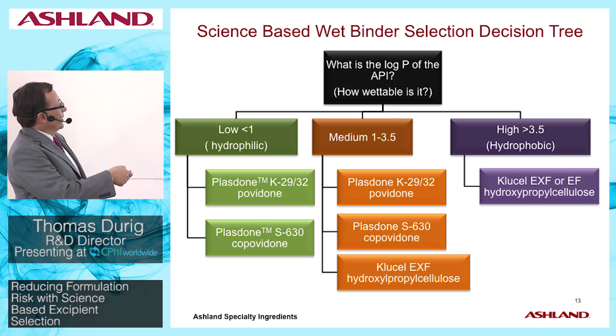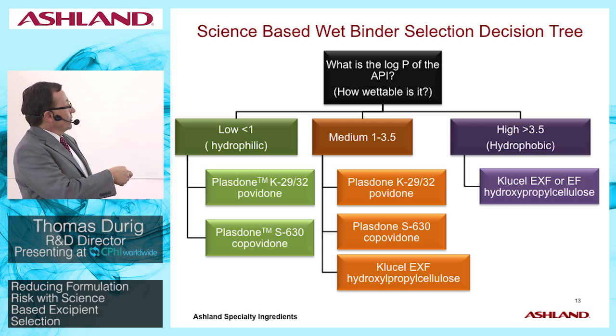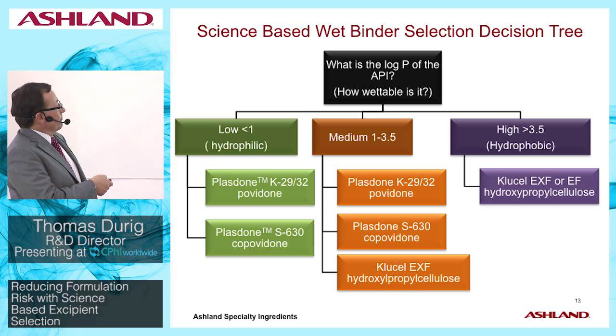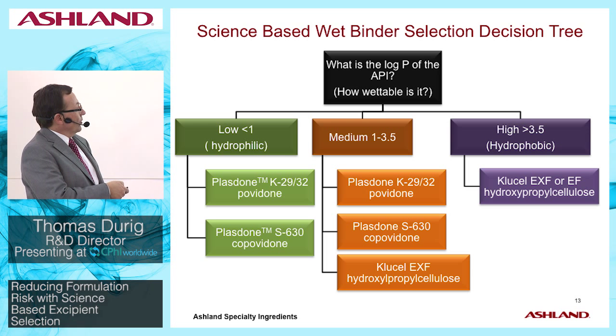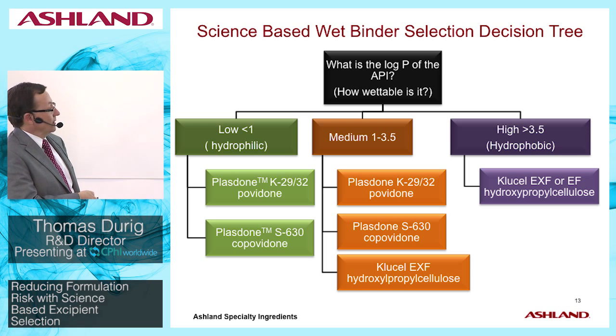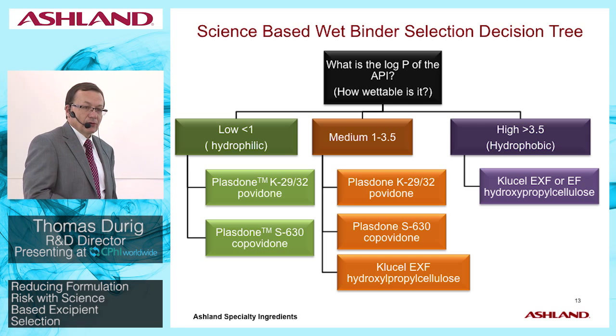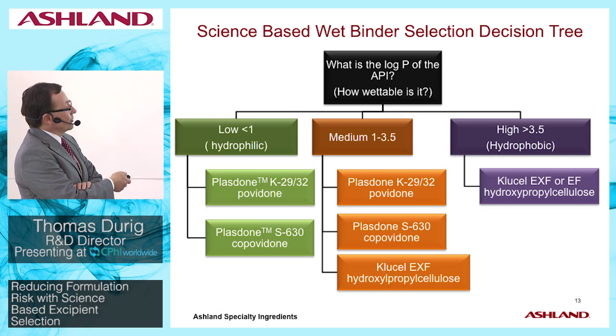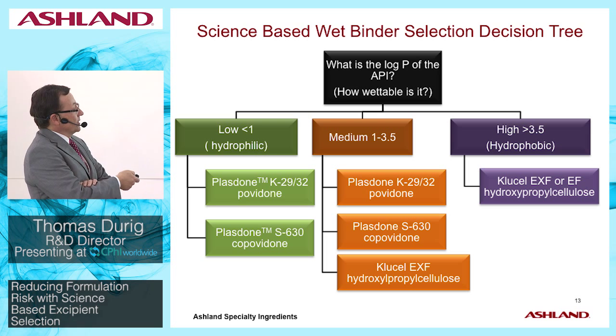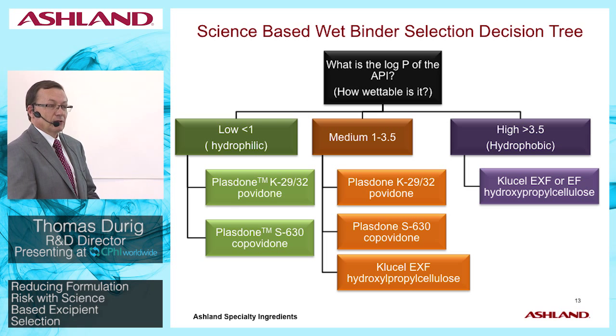In the case of a low log P and a very hydrophilic API, maybe less than 1, Plasdone, PVP, or copovidone would clearly be the ones we would recommend. If there is a medium hydrophobicity in this range here of log P 1 to 3.5, either Plasdone, PVP, or Klucel HPC would work equally well. And for a very high log P API, we would typically recommend Klucel HPC.